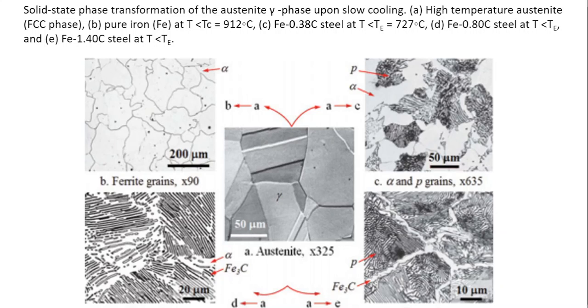So the average carbon percentage here moves towards the eutectoid composition. Consequently, when this alloy is homogenized at a temperature lower than the eutectoid temperature, the remaining portions where the cementite hasn't occurred convert into a perlitic structure.